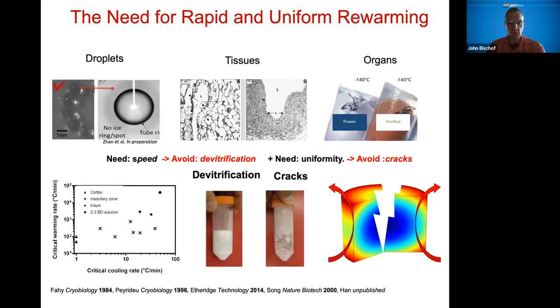And so you can see this on all scales, whether it's from droplets to tissues to organs. So you're going from something that might be a millimeter or less to centimeters in the case of organs. And how do we get uniform and rapid rewarming? So again, you can see your failure modes in the middle, devitrification or cracking. And one important thing here on the bottom left is that there's a critical cooling rate. That critical cooling rate is what Greg was able to already do back in the 80s, which is to basically, you get enough of this cryoprotective agent in, then you have to cool it sufficiently rapidly that you can actually reach the vitrified state.